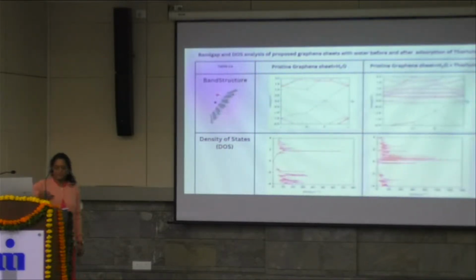Similar to this, we then have the thorium atom. When we kept the thorium atom near the surface of the graphene sheet, we found a band gap has been introduced. It's a direct band gap here, and the states have also changed. The DOS has been significantly changed.